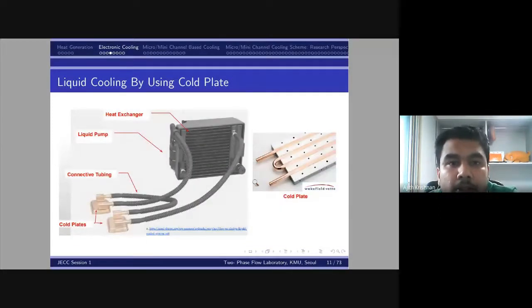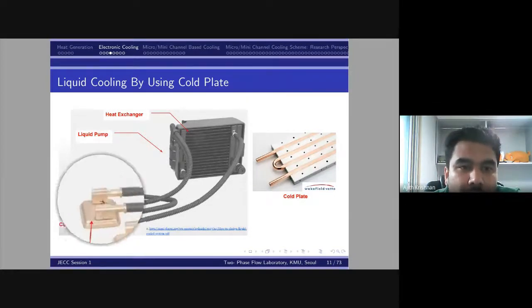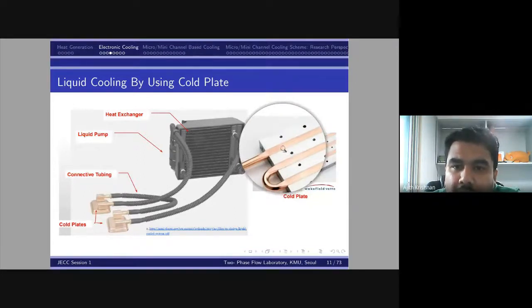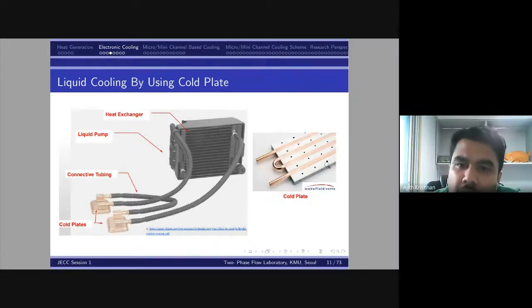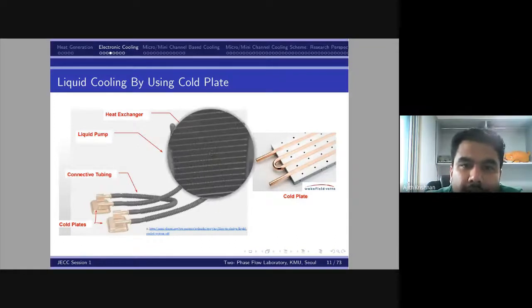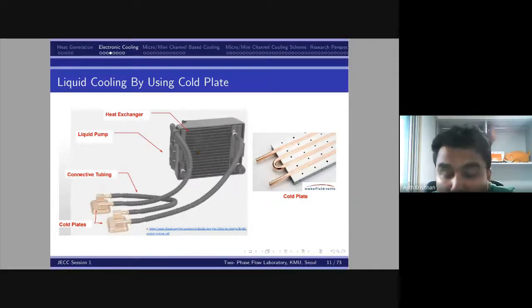Okay. So another method of cooling came, that is what is called liquid cooling. In this case, the liquid will not be allowed to contact the chip directly. Here what they will do is provide a cold plate. You can see a cold plate here at the end. You can see two cold plates here. The cold plate will be like this, a flattened plate along with tubes attached. This will be a single surface, and this will attach to the processor surface. So what will happen? The fluid will be flowing through these tubes. Along with that, it will take away the heat from the block and also directly from the tube, and that liquid is to be cooled by using a heat exchanger like this. This is what is called the liquid cooling method by using a cold plate.